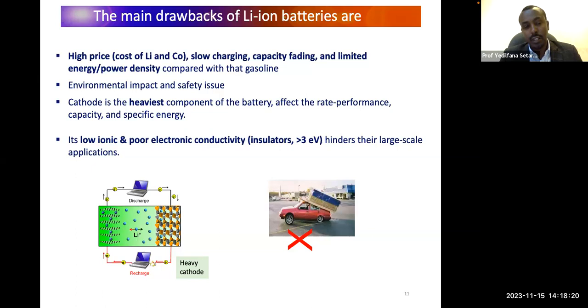So if you want to have high capacity, high specific energy, when you say specific energy, it is the amount of energy per kilogram of the mass of the active material. So the material should be as light as possible. But unfortunately, the existing cathode materials are heavy due to the presence of these transition metals and the like. So they are heavy, and at the same time, they also have poor ionic and electronic conductivity. So these are the main challenges, and we are trying to tackle this problem by employing advanced computational methods, which I will talk about later.